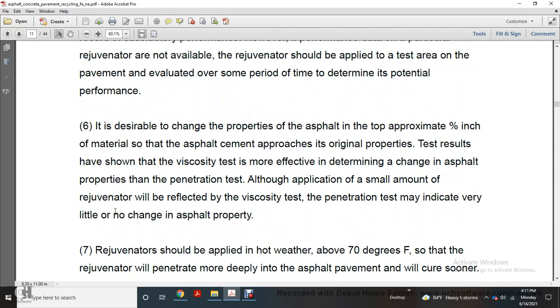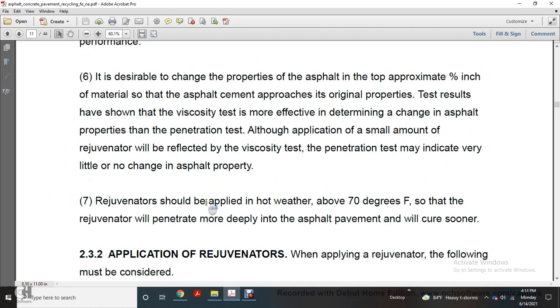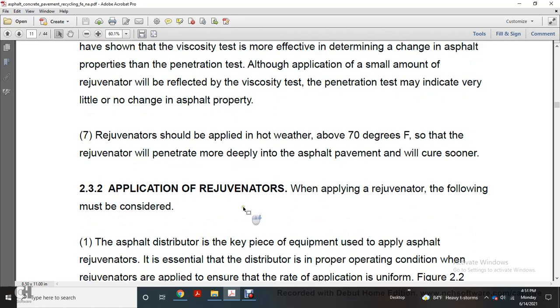6. It is desirable to change the properties of the asphalt cement and approach the original properties. Test results show that the viscosity test is more effective than the penetration test in determining the change of the asphalt properties. Although application of a small amount of rejuvenator will be reflected by the viscosity test, the penetration test may indicate very little or no change to asphalt properties. 7. Rejuvenator should be applied in hot weather above 70 degrees Fahrenheit so that the rejuvenator will penetrate more deeply and the asphalt pavement will cure sooner.